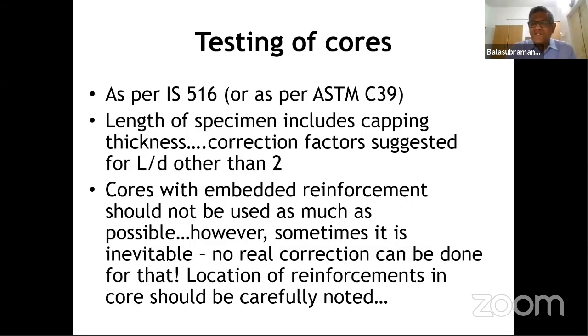One is cutting of the reinforcement during a core test. Designers will not be happy about it. Second, a core with an embedded reinforcement may give you a very erroneous result. If the bond is not good and all that, then they may not give you a proper result. So as much as possible, try to avoid cutting of the reinforcement from all perspectives, from the designer's perspective, as well as from the core concrete strength perspective.